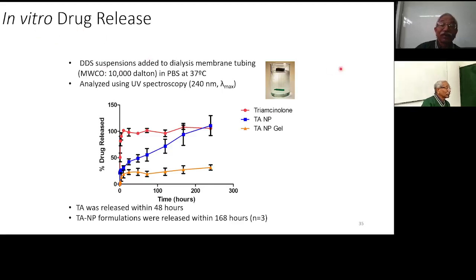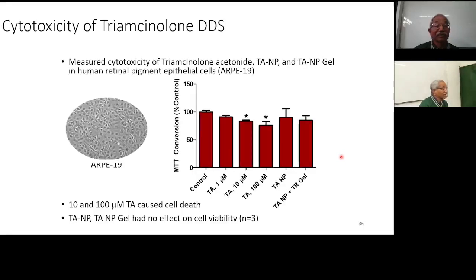So we did in vitro drug release. Now you can understand, this is our drug delivery system. We used 20 milliliters of the liquid, so you will never get that, and whatever release profile you are getting will be much more extended. So our triamcinolone was released within 48 hours, and the triamcinolone nanoparticle formulations were released in 168 hours. So this is the sustained release we could see. And we used UV spectroscopy to analyze the drug content in the nanoparticle.